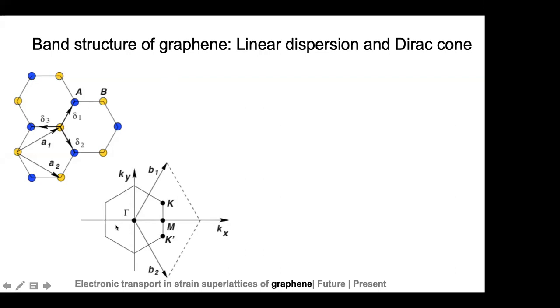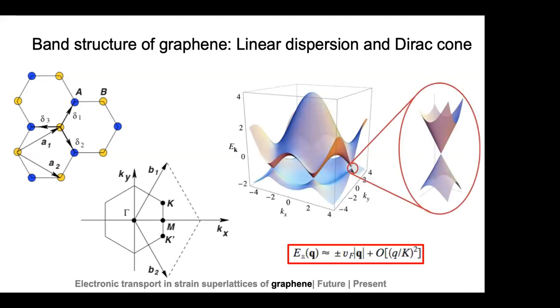When you use the tight binding Hamiltonian, considering just nearest neighbor interactions, and solve it, you'll find that the energy of the system varies linearly with the momentum. And this linear dispersion relation is quite famous for graphene. Because what happens is, you have the valence band and the conduction band, and they meet at the 6 points, the 6 K points on the Brillouin zone.